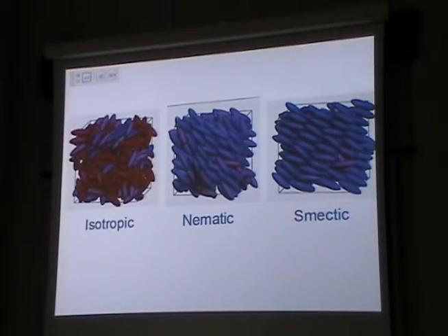I'm just interested in roughly what direction they are pointing in, and also what their properties are. You can see from the models, we have random isotropic at high temperatures. We cool it down a bit, we get this kind of one-dimensional orientation order, where they're all pointing in one particular direction. And then when we get to the smectics, we have this common direction. We also have now these layers appearing, order in this dimension, which shows we're heading more and more towards a solid crystalline structure. I'm just going to use these two as a very simple way of describing some of the optics of liquid crystals.